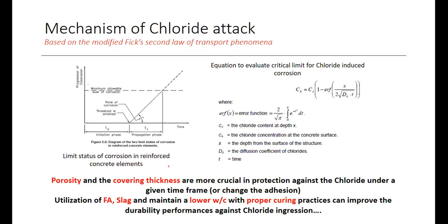Addressing the porosity and the cover thickness are the more crucial factors against chloride diffusion. Or we can apply some sort of non-permeable coating on top of the concrete layer, like a paint or different kinds of coatings. With utilization of fly ash or slag, a low water-cement ratio and proper curing, we can improve the durability performance against chloride invasion.